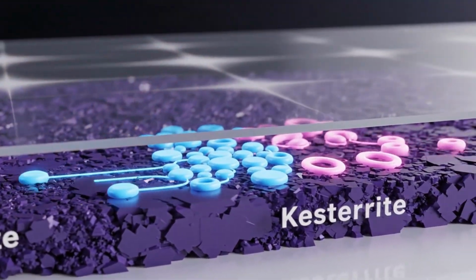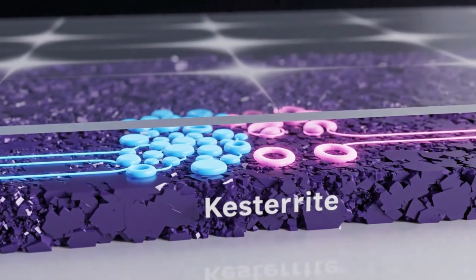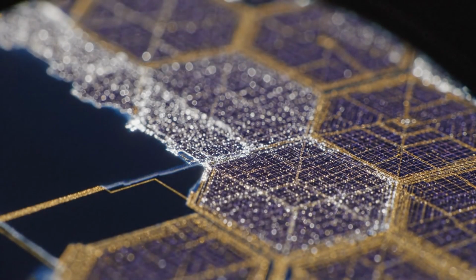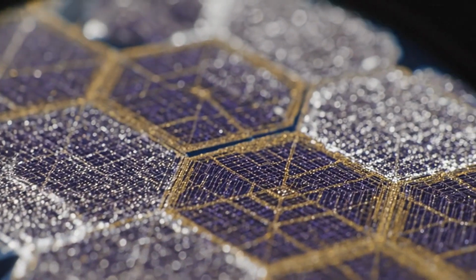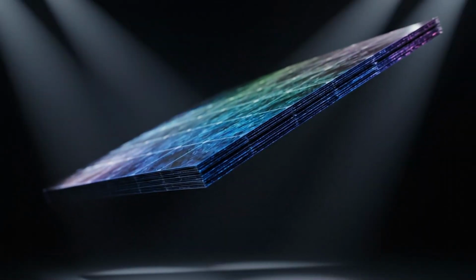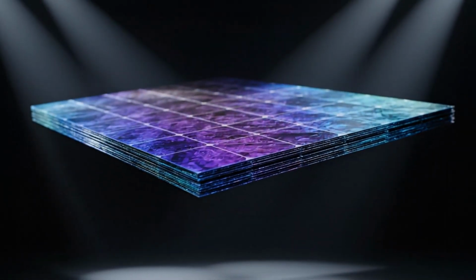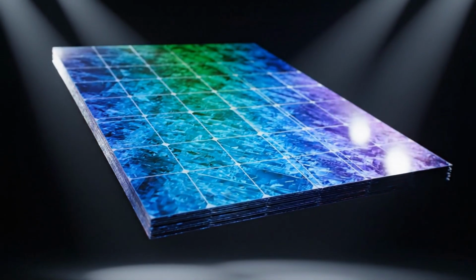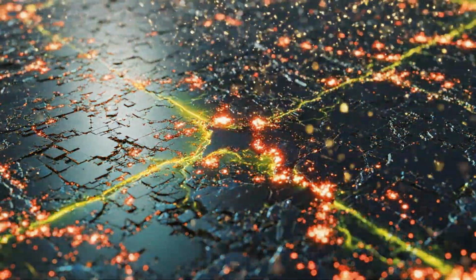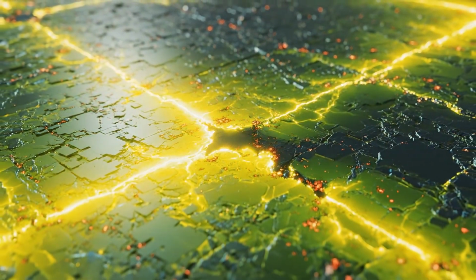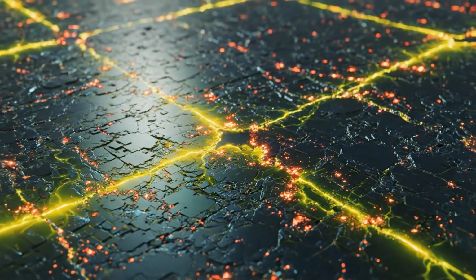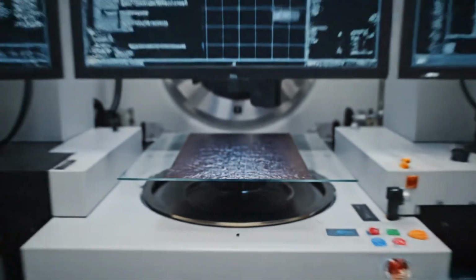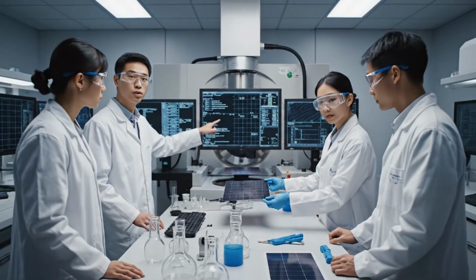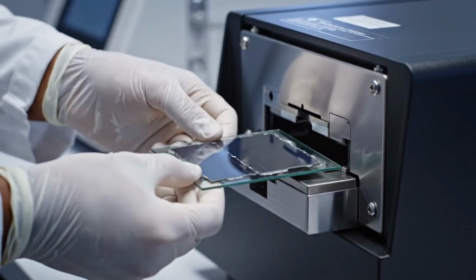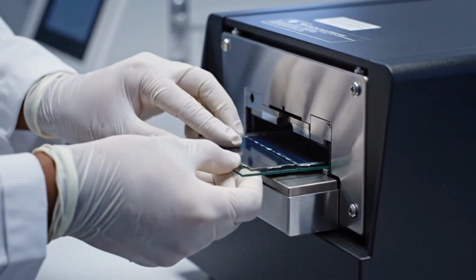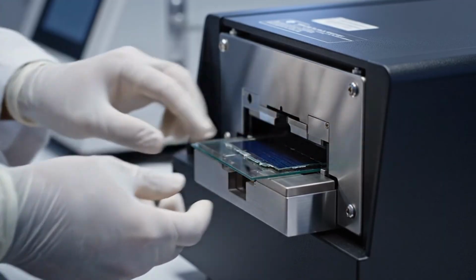But here's where kesterite surprises again. Recent record-setting kesterite cells were produced using solution-based manufacturing techniques, methods that are faster, cheaper, and far more scalable. One standout example is a process that's conceptually simple: applying excess material, then physically removing the surplus to achieve uniform thickness. It's low-tech in appearance, but incredibly effective. And it points to a future where kesterite could be manufactured using processes similar to coating, printing, or roll-to-roll production. That matters because energy transitions don't scale on efficiency alone. They scale on cost per square meter.